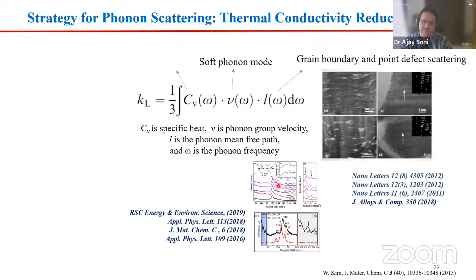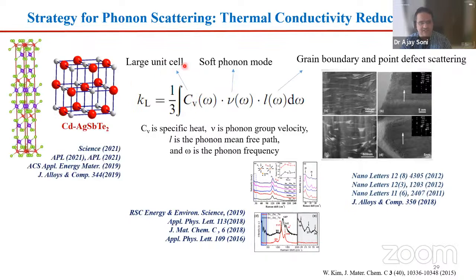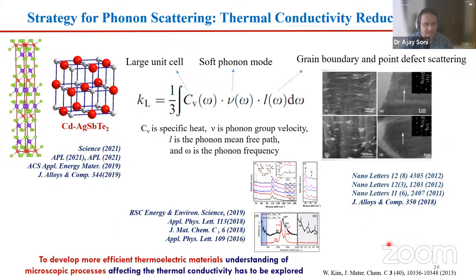We also work on some materials like SnTe-based material, where we found that you can reduce the lattice part of the thermal conductivity by creating some defects. Okay, so we actually broke some of the inversion symmetry of these materials. These are cubic materials, and we actually disturbed the overall group velocity of the phonons. And now we are working on some materials which have poor heat capacity, like large unit cell materials, and there you can tap in. So we actually control all these three parameters to get the poor thermal conductivity in these materials, and these are some of the publications from our group and the collaborators which came out of this particular research.